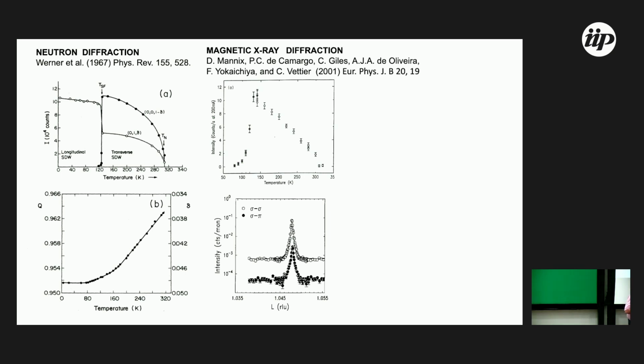The X-ray interaction with the magnetic moment, and its intensity in comparison with the charge density wave, which is a direct interaction of the X-ray radiation with the charge of the electron, is about 1 in 10,000. It's a very difficult experiment, needing many counts for observation. But the importance of this experiment is to observe the polarization of the X-ray and the effect of the component of the magnetic moment of the spin density wave. This paper shows that the magnetic moment associated with the spin density wave is due only to the spin, not the orbital moment, because of the experiment's direction, the polarizations sigma and sigma-pi, in this chromium sample.